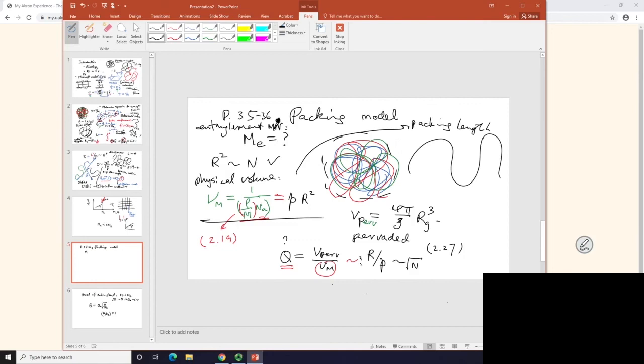So I will upload the papers. For example, to give you a sense, P is about 1.6 for polyethylene. P is nearly about 4 for polystyrene. I didn't give you a unit. What unit? Angstrom. With that benzene ring, it looks very bulky.